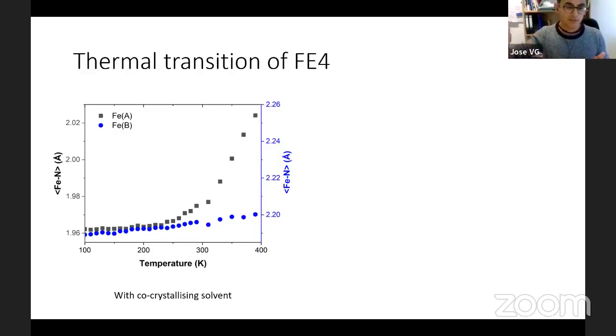one of the metals. We call it iron A, which is the one having the transition from low spin to high spin, while the iron B, which is usually always in the high spin, remains all the time in high spin. So there is no significant bond length expansion. The bond length expansion is linear and very small. So with co-crystallizing solvent, we see nothing really exciting, even if we go below 100K, which I didn't report in my first paper.